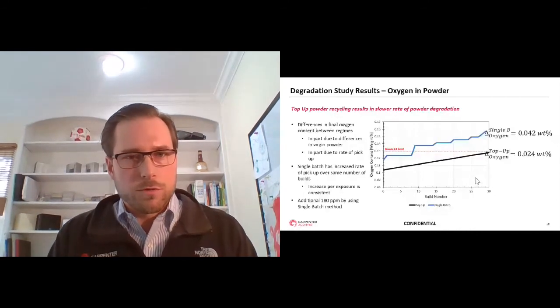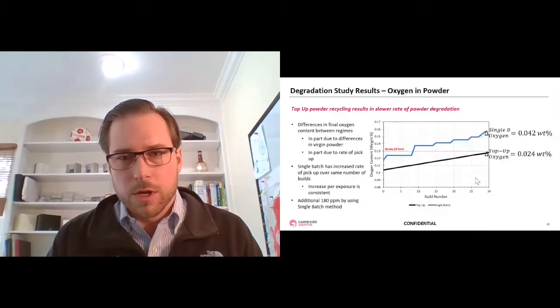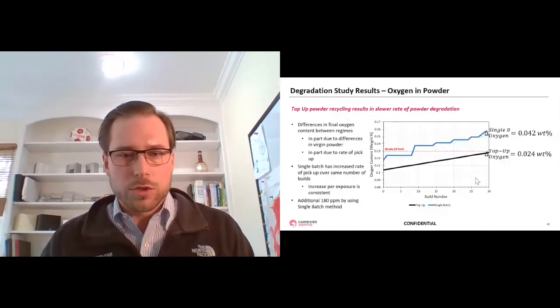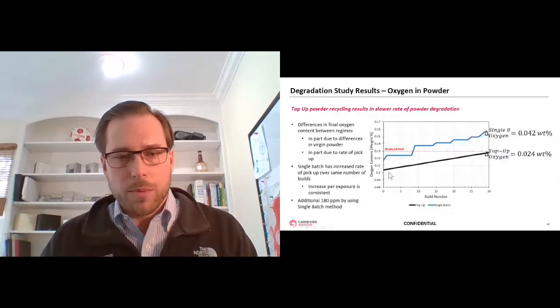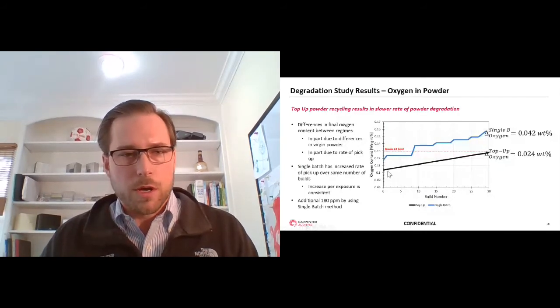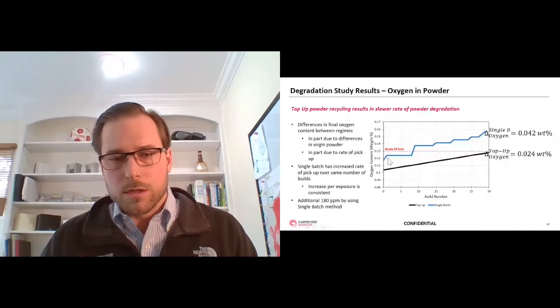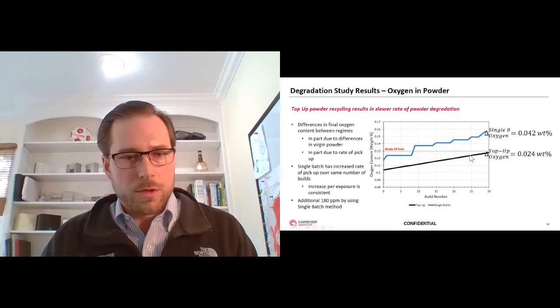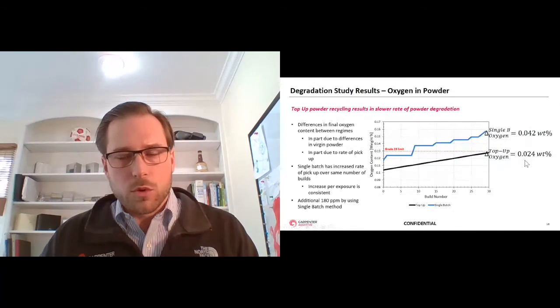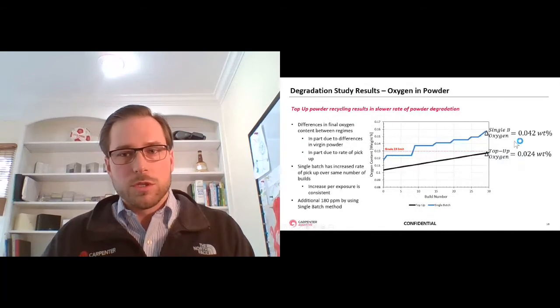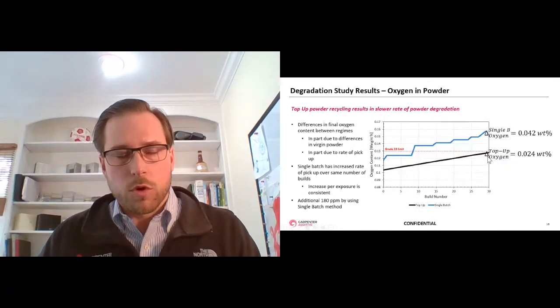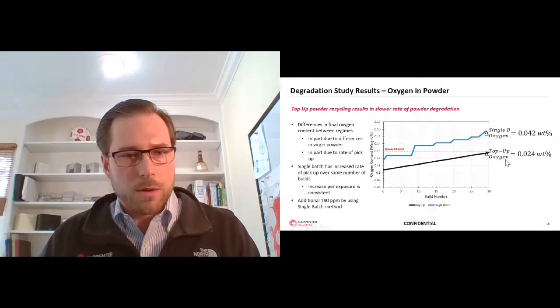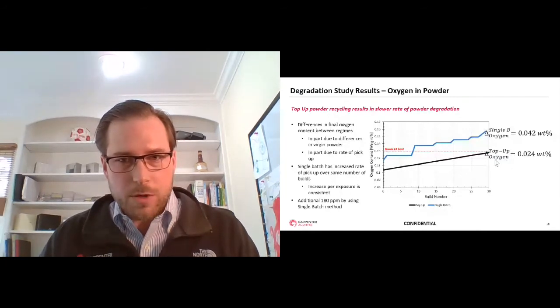So the first result that we're showing here is the oxygen content in the powder. What you can see is the blue line shows the single batch method, and the top up method is shown on this black line here. And what you can see is a much sharper increase in the single batch method than the top up method. So roughly, we're talking about almost twice the amount of oxygen pickup, and an increased rate on the single batch. It's tough to see here, but the gradient of this line is actually steeper than this line.